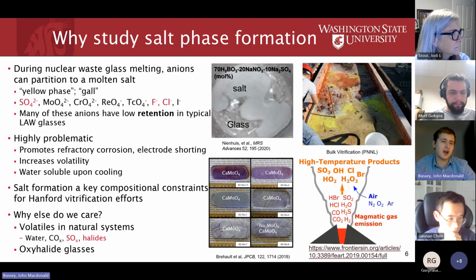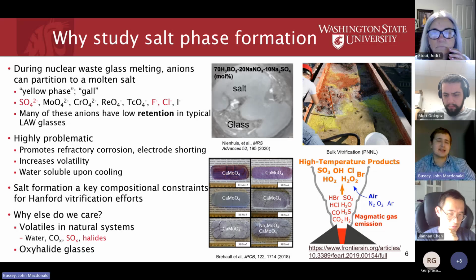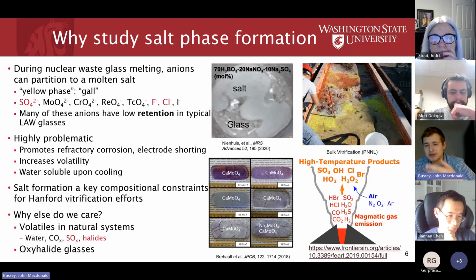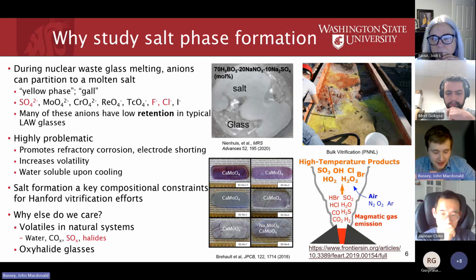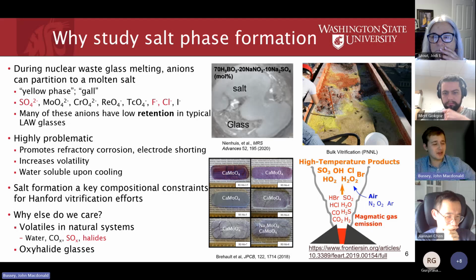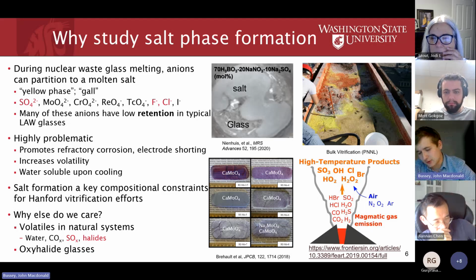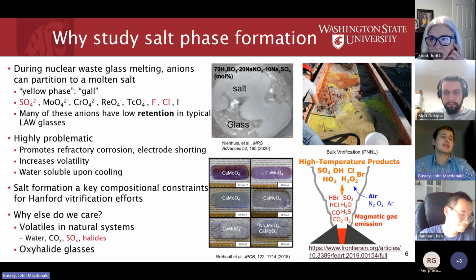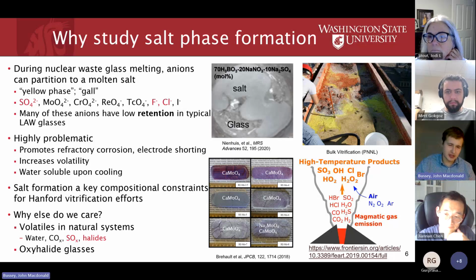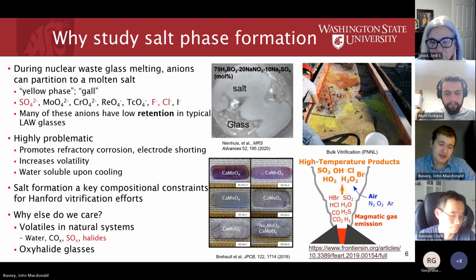If this salt phase forms, often called yellow phase or gall, it's really quite nasty. The main concern is that since it's a very corrosive liquid, it corrodes the refractory lining of the melters. But these melters are $1 million pieces of equipment, and if you have to replace them often, you can't just replace the lining, you have to replace the whole instrument. But that's possibly the least of the concerning issues of salt.